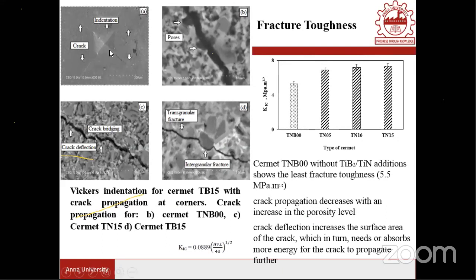So we have measured this length, and substituting the length, and also the load at which the hardness value is taken, and also the hardness value, one can measure the fracture toughness value. The fracture toughness value for the standard tool that we have considered is only 5.5 MPa root meter. Normally for TiCN, as an individual TiCN, if you sinter, the maximum toughness value would be 6 megapascal root meter. That's all. It's a poor fracture toughness value.